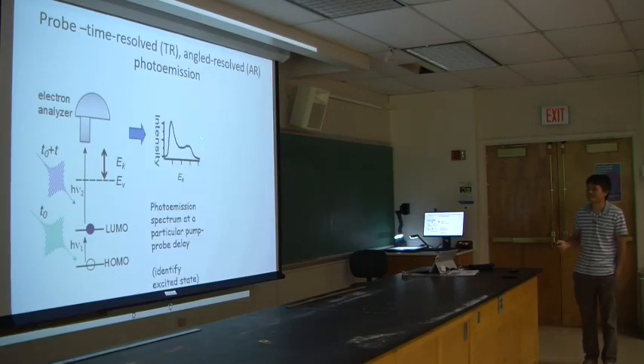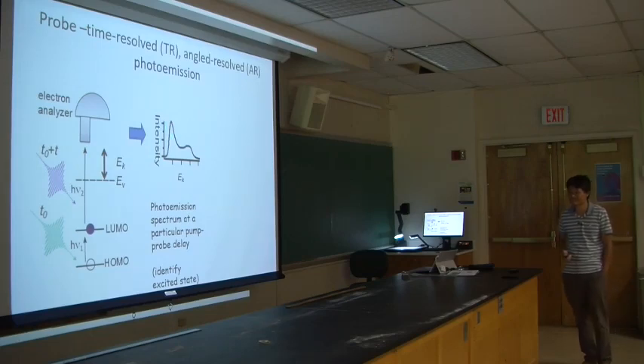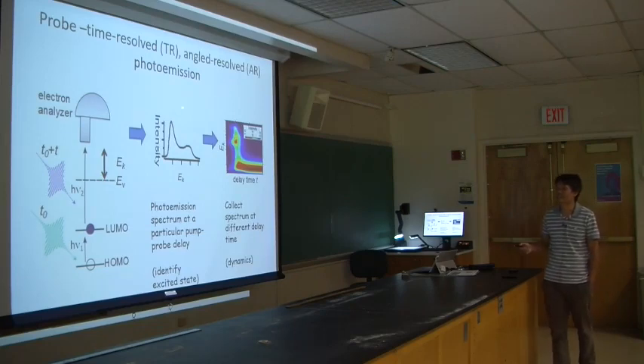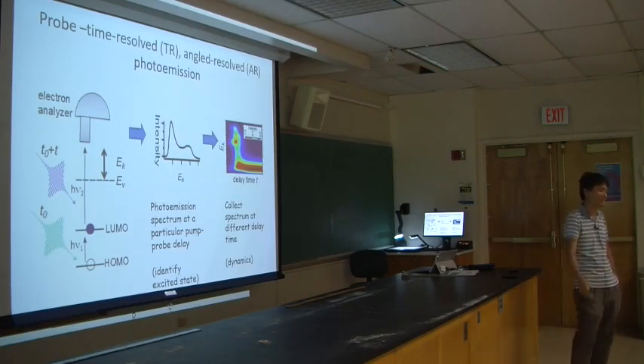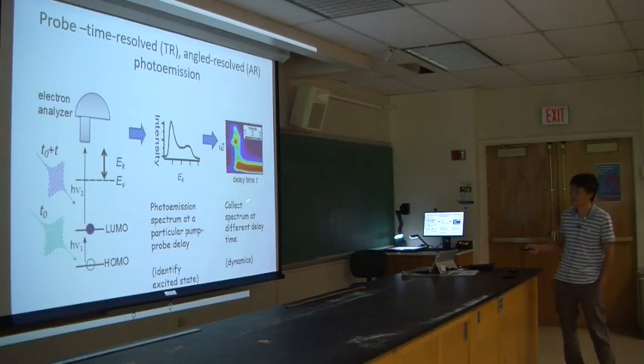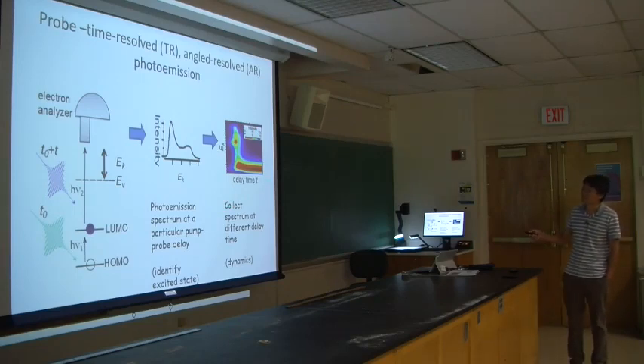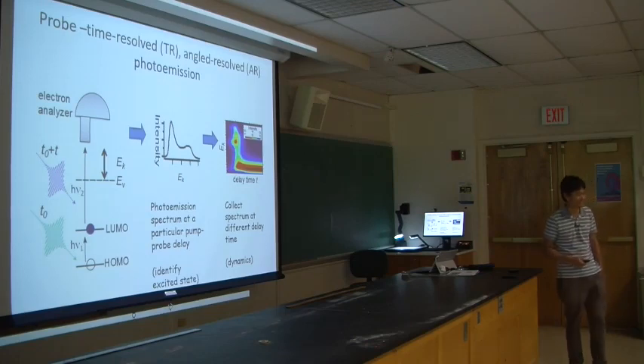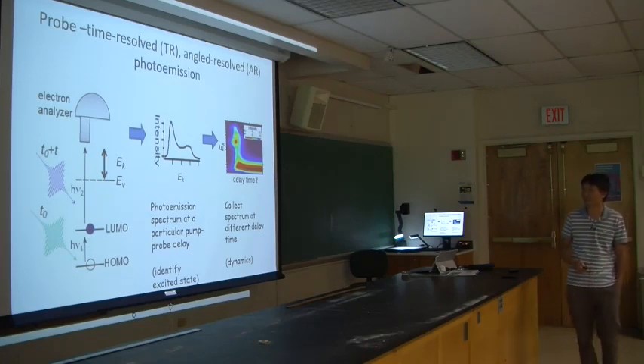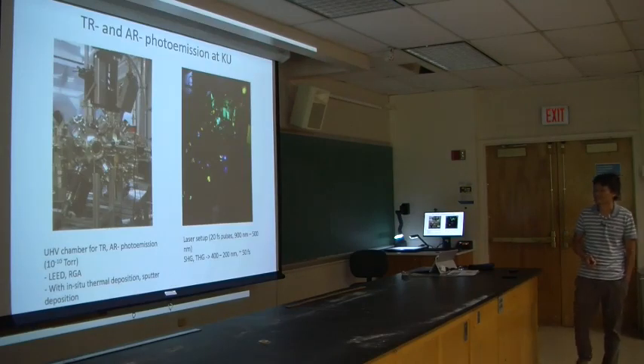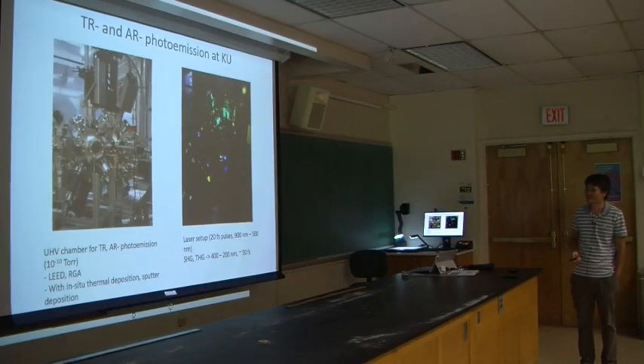Here is a typical photoemission spectrum. We have intensity and energy, and different energies represent different states, right? Of course you can collect this spectrum at different delay times, and we have this kind of 2D spectrum. Here is time, here is energy, right? So you can look at the dynamics of different excited states as a function of time. So that's the tool that we are using. That's just some pictures of our lab. These are the photoemission chamber and the laser setup.